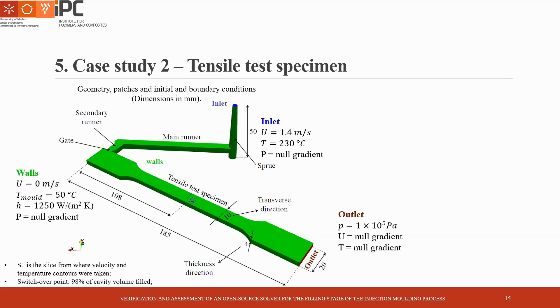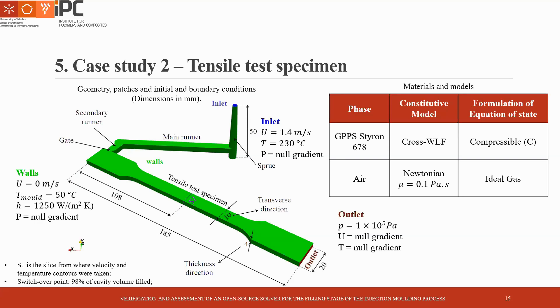In the second case study, a tensile test specimen with feeding system was employed to make a direct comparison between Open-Inge MoldSim and Moldex3D. It is a geometry widely employed in industry for material mechanical characterization, and with this case study we intend to create a case study that could be replicated experimentally. The initial and boundary conditions are the same as the previous case study, with the exception of the inlet velocity, which is now defined as 1.4 meters per second. The switchover point was again defined as 98% of the cavity volume filled, the Styron 678 with Cross-WLF was used, and only the compressible formulation was selected as it gives the most realistic results.